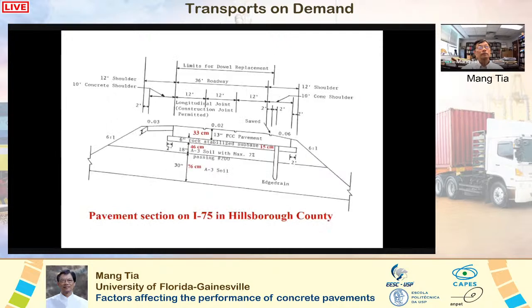This is a typical design used by the more recently built concrete pavements in Florida. It has a thick concrete slab with a thickness of 33 centimeters. The concrete extends 2 feet, which is equal to 61 centimeters, into the shoulder length in order to reduce the maximum stress on the concrete slab.